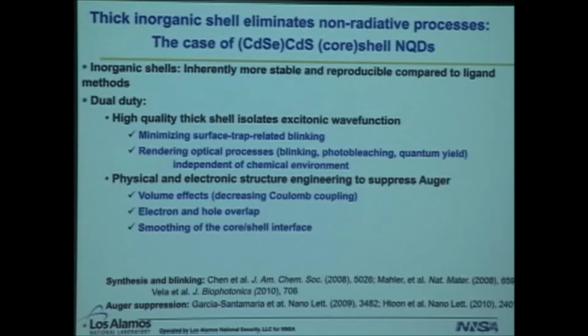And even though a thin shell system was definitely shown to go in the right direction, it just hadn't been taken far enough. But in a more subtle area, we hoped that if we did this shelling procedure correctly, maybe through especially electronic structure manipulation, we would also be able to address the issue of Auger. Auger can be influenced by a number of factors. First is the volume effect. If you decrease Coulomb coupling by increasing the size of your nanostructure, that itself will reduce Auger recombination.